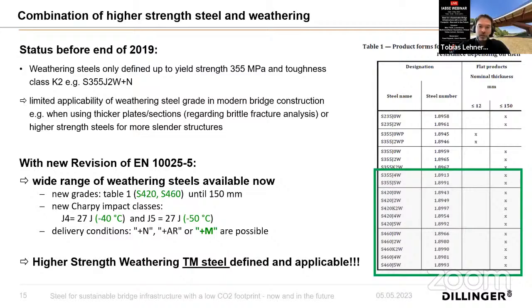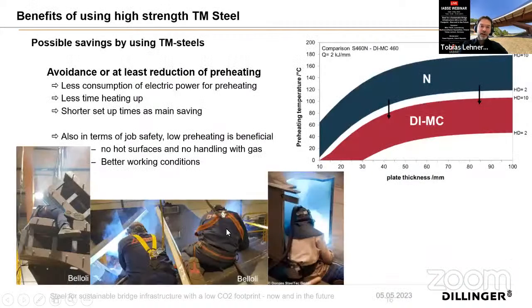We have a wide range of weathering steels now available, also up to 460 steel strengths, and also with minus 50 degrees Charpy impact. And very important, also with the delivery condition thermomechanical rolled. And so nowadays we have a higher strength weathering TM steel defined and applicable. And here again, it is very important that it is now allowed to use thermomechanical rolled steels, because these TM steels again have benefits, one thing is in the steel production, but also later in the fabrication, in the bridge building, in the workshops.